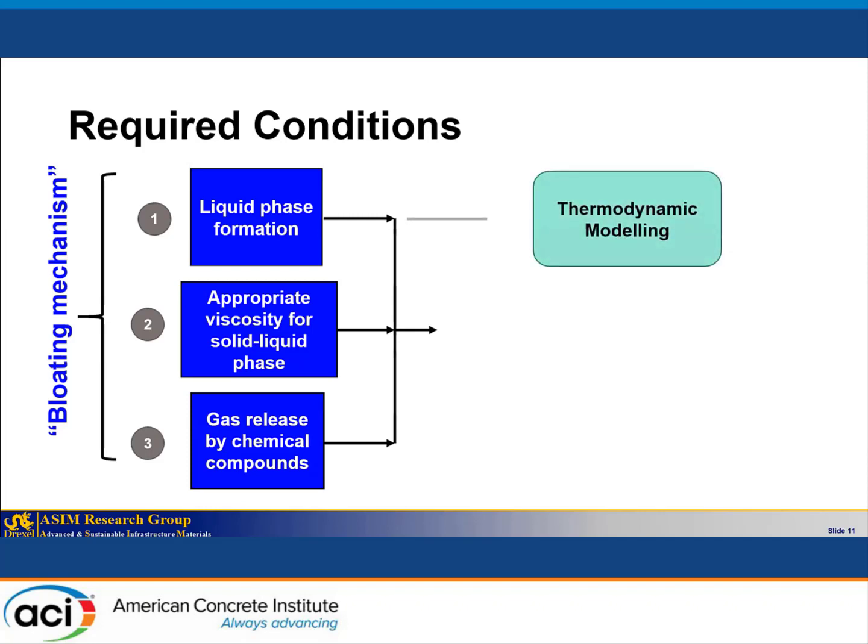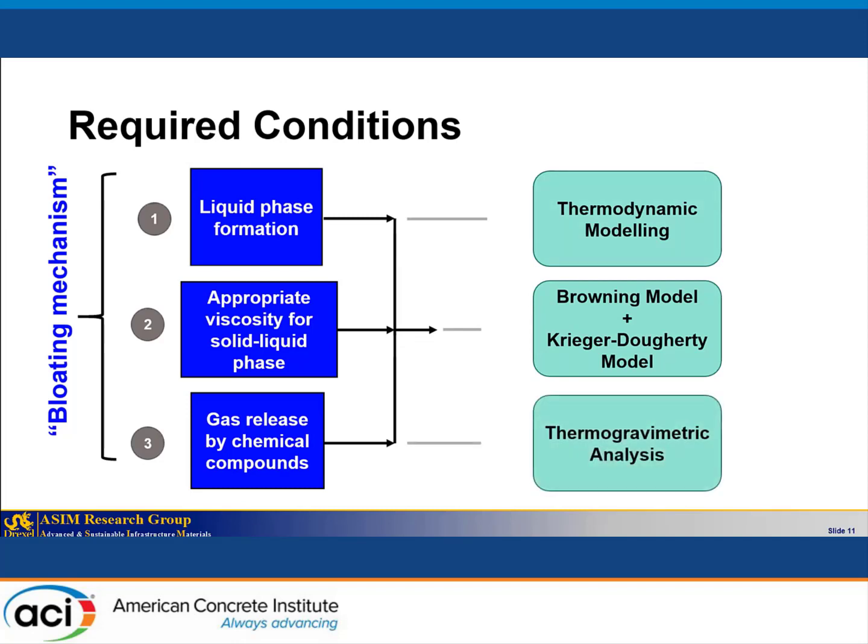parameters? For liquid phase formation, we use thermodynamic modeling to quantify the liquid phase formed in a material. To estimate the viscosity of the solid-liquid phase, we use the Browning model and the Krieger model, which I'm going to go into detail in the next few slides. And for gas release measurement, we use thermogravimetric analysis.